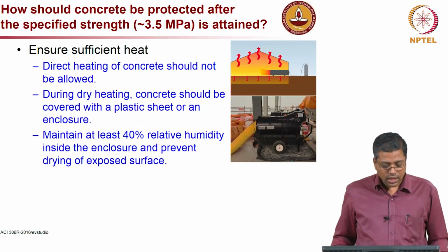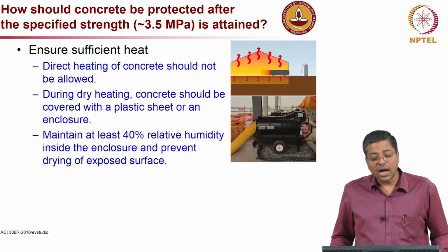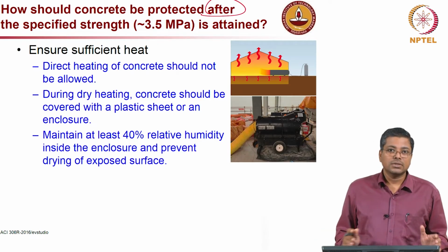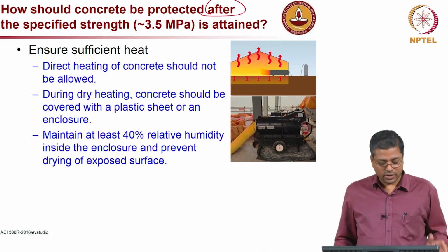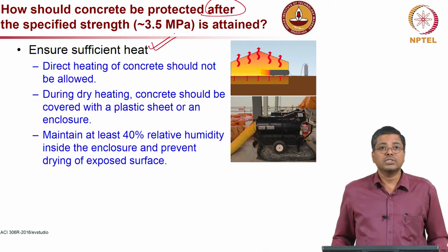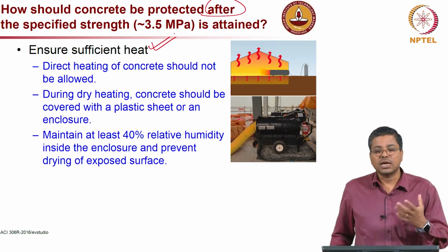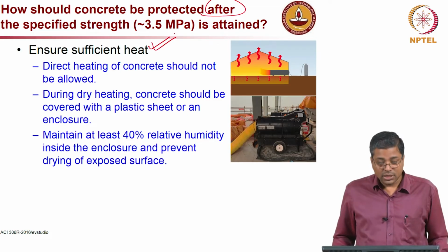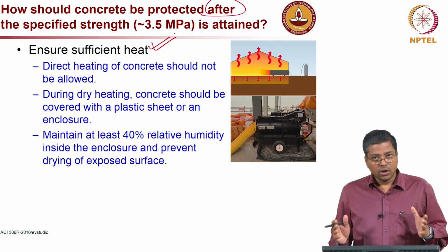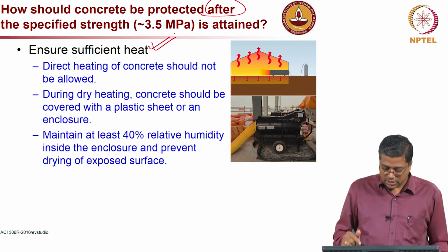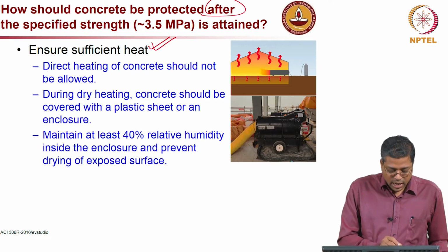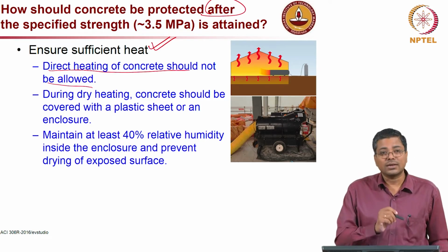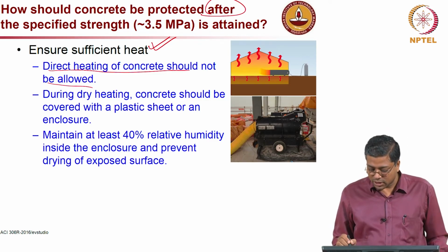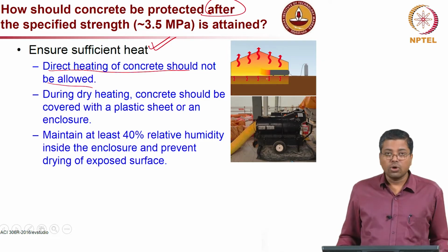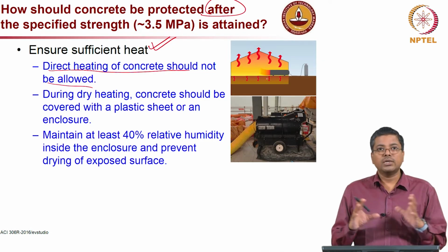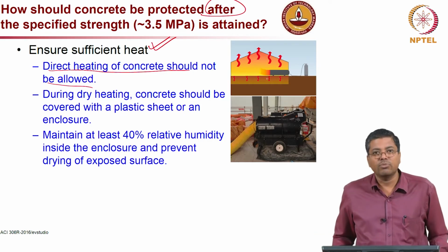water curing compound. Now, how should concrete be protected after the specified strength is attained? That is slightly not in the very early stage, but after that. How do we ensure? Mainly by ensuring that sufficient heat is available, or the heat which is coming from the concrete is not lost into the environment, and also you can provide external heating to the concrete. In this slide we are talking about external heating, which is direct heating of concrete should not be allowed. As you see in the picture on the top right, there is a flame and then there is an enclosure on top of the concrete surface, which provides hot air uniformly around the concrete surface.